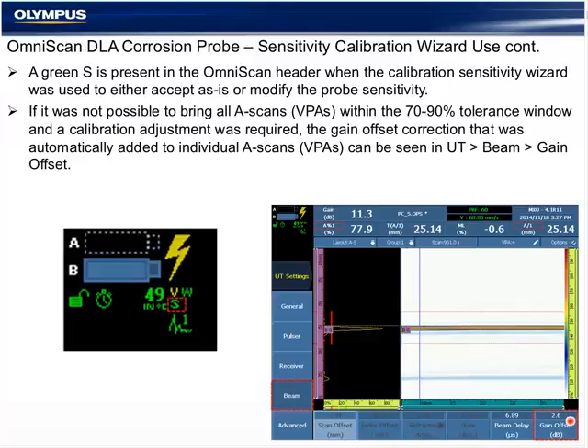If the probe came from the factory and is within the specs on your probe certification sheet and has not been damaged, it would normally not require any calibration for sensitivity. In other words, if your coupling and pressure points are correct across the probe, we should easily be able to maintain the sensitivity of each A-scan on a flat block or reference sample or pipe sample at 70 to 90% across the whole probe.